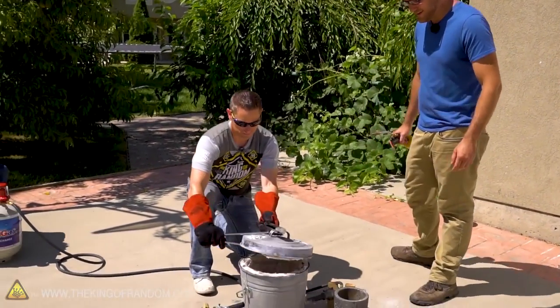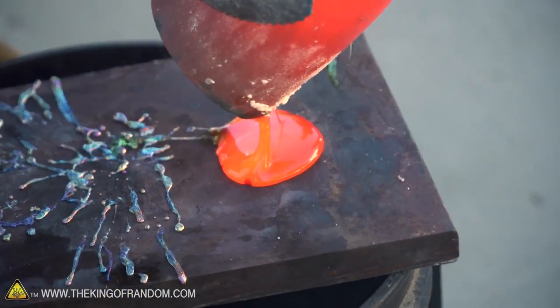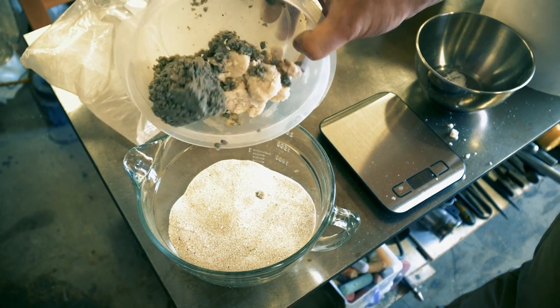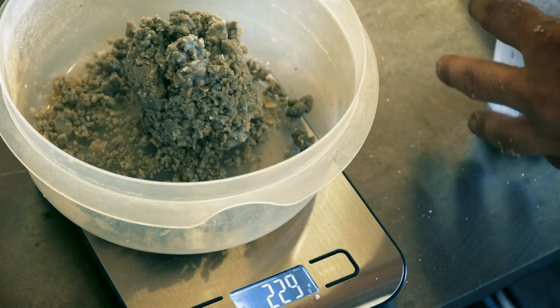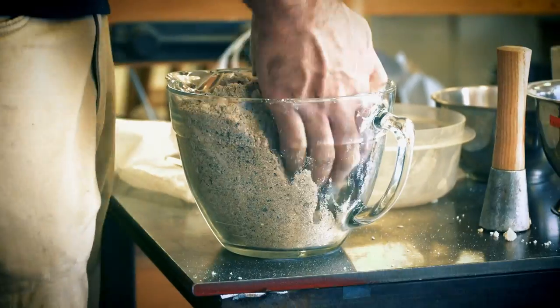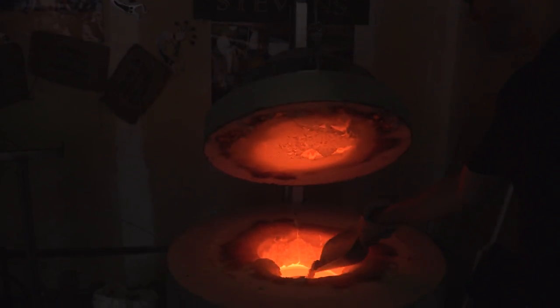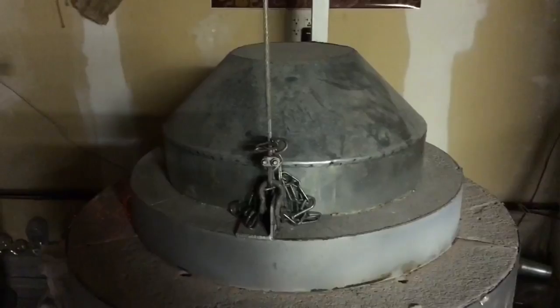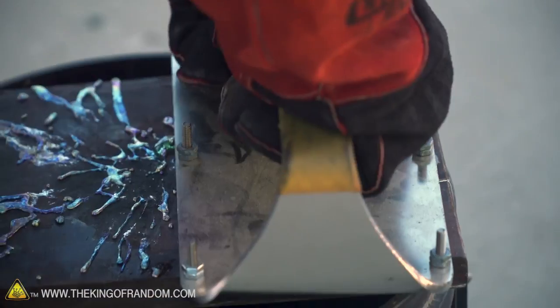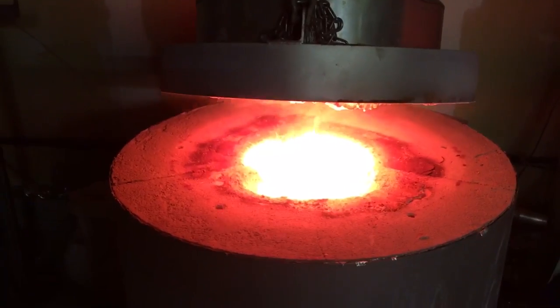One of the biggest variables on this trip was whether Grant's forge was going to be hot enough, something that's been a limiting factor in some of my other attempts. In case the attempt with him failed, we contacted a glassblower in Utah to use their kiln for a backup batch. There we put together a batch of some of my original sand, the soda ash extracted from glasswort, a little bit of the natron, as well as a little bit of salt from the Redmond salt mine. We left that batch in the kiln for over a day to slowly bake and hopefully produce some clear glass. Unfortunately, the glassblower got freaked out by a large amount of steam the batch was emitting and pulled our batch out prematurely. Lucky for us, the glass made with Grant actually turned out quite well, but I want to keep refining my skills and see if we can salvage the backup batch and finish melting it into something.